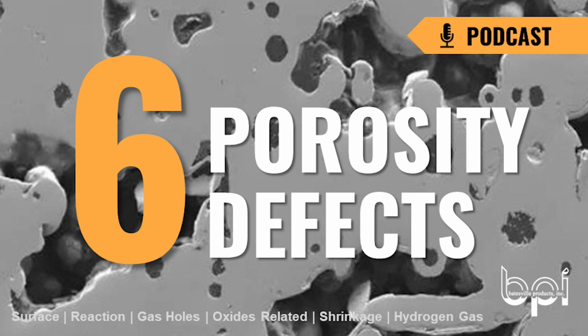When the hydrogen reaches the surface, it actually burns off. So if you have a lot of hydrogen, you actually see flames on the surface. The chlorine and the SF6 actually chemically combine with the hydrogen, but bring it to the top in the same manner. There's two main factors, and one is the moisture in the air. So the higher the humidity, the faster the hydrogen is going to go in. And number two is the metal temperature.